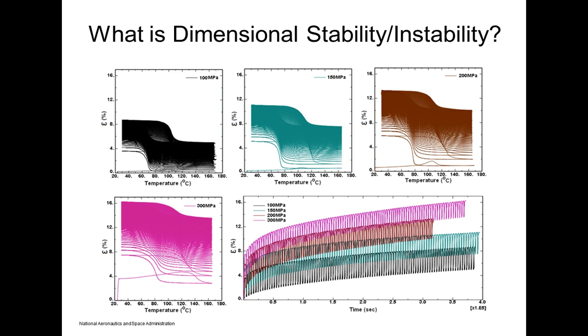What we can say is that clearly the lower the amount of deformation that we require out of the system relative to its maximum capacity for transformation, the longer life the system will have. And in the automotive sector, they know this greatly in the sense that they're using alloys that might do in a polycrystalline aggregate 4 to 5% maximum transformation. They're designing the systems to run at only about 1 to 2% or 1 to 1.5% transformation, and they're getting millions and millions of cycles out of these systems.